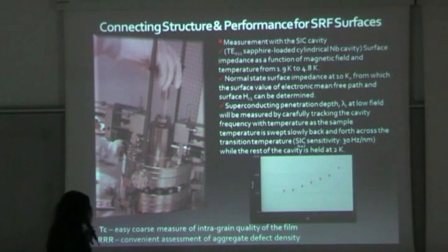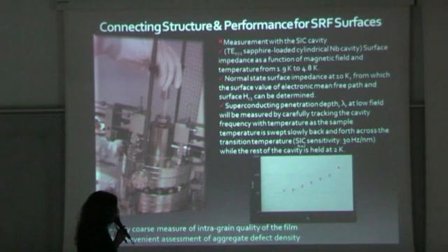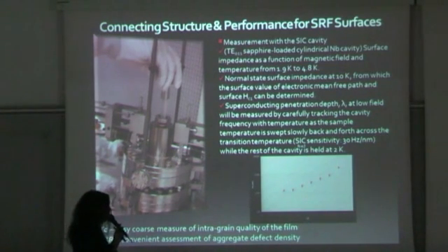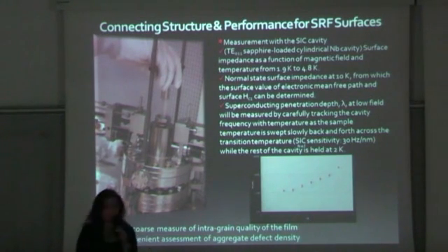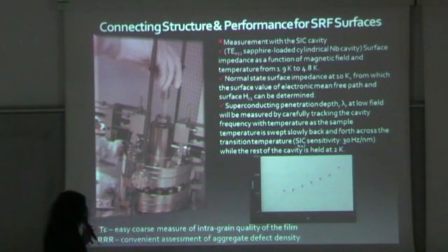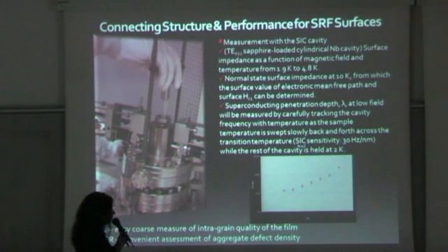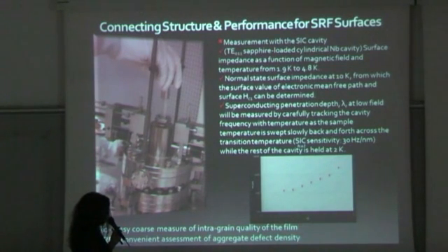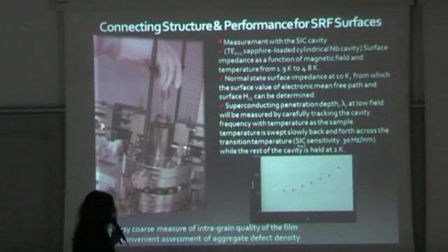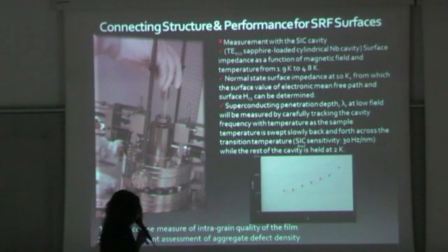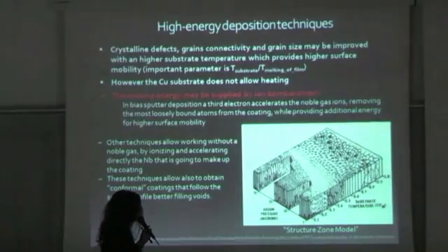Of course, we cannot do this work without RF measurements — you need to know the RF properties of your film. One of the instruments we use is the surface impedance cavity discussed in Charlie Reese's talk on the first day. It's a TE011 sapphire-loaded cylindrical niobium cavity that works at 7.5 gigahertz, with which we can measure surface impedance as a function of magnetic field while varying temperature from 1.9 K to 4.8 K. We can also measure normal resistivity and penetration depth. We also use Tc and RRR measurements in DC mode to characterize films on insulating substrates.